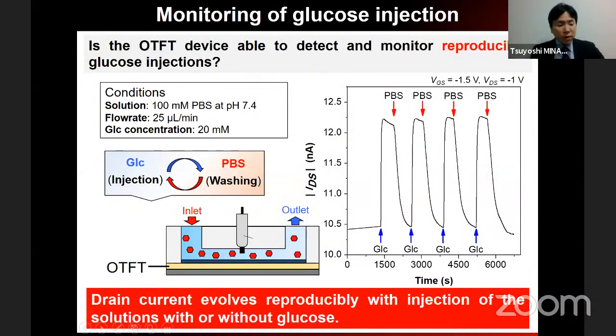After we fabricated the device, we injected glucose and then washed with phosphate buffer solution. After we inject the glucose, we immediately observe the drain current change. But after we wash with phosphate buffer, the signal immediately goes back to the baseline. So this is repeatable. That means our organic transistor with the microfluidic system can continuously monitor glucose.